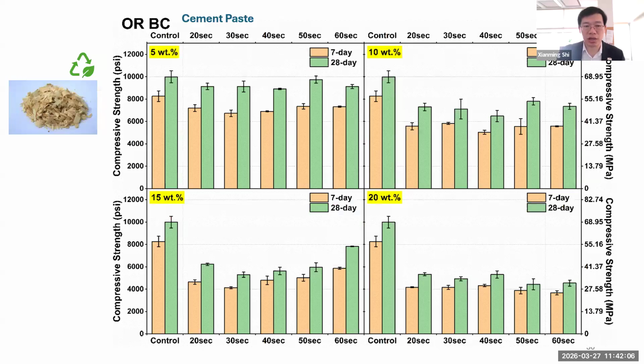And for this softwood chips derived biochar from Oregon, I know it's a very busy slide, but we basically tried different dosages, 5, 10, 15, 20%. And the different color bars show 7-day strength versus 28-day strength. And then we also tried grinding it for different durations, in other words, achieving different size gradation, to see how that would affect the compressive strength of the cement paste incorporating such biochar products.